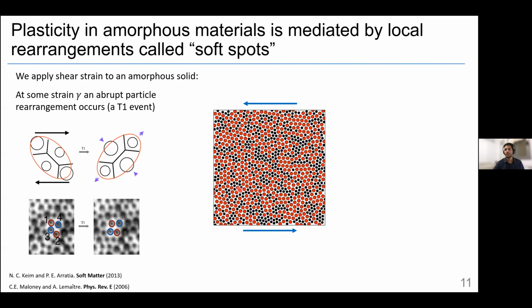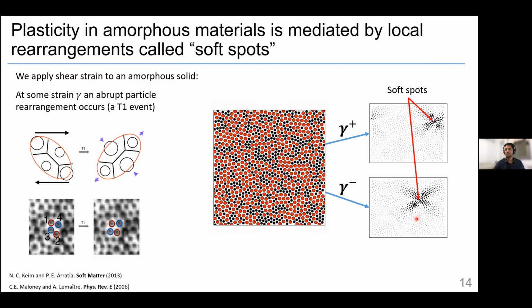What happens is that when it occurs, at some value, which I call gamma plus here, you get a displacement field that looks like a quadrupole, where the T1 event is in the middle. And if you take the same sample and shear it the other way, for example to some gamma minus, you get another quadrupole at a different location. So this is a different plastic event. So from the same configuration with different strain thresholds, you can get two soft spots, as we call them, with different displacement fields. This one is smaller, but both look like a quadrupole.